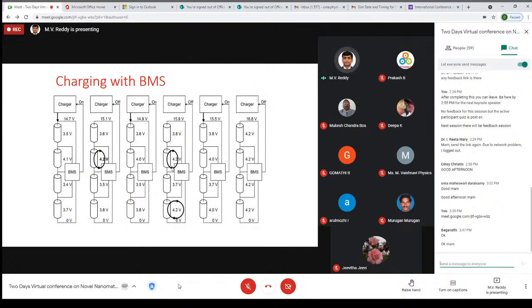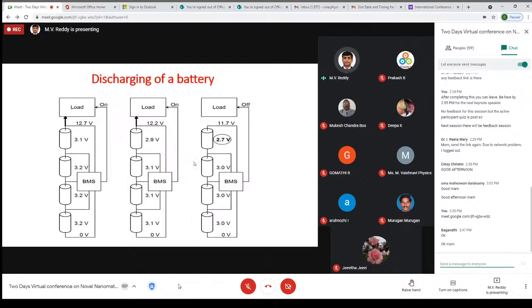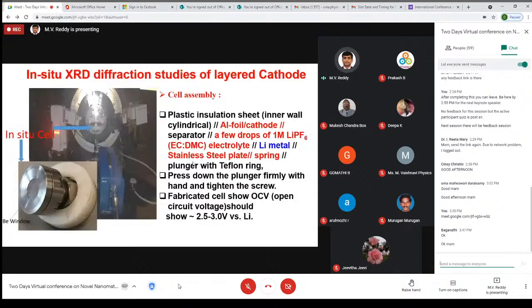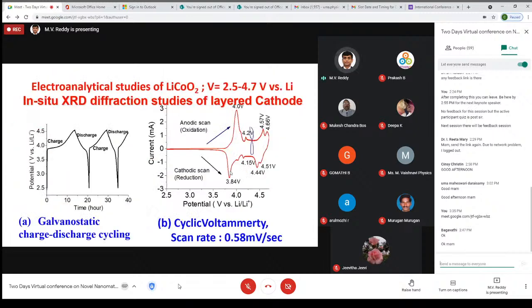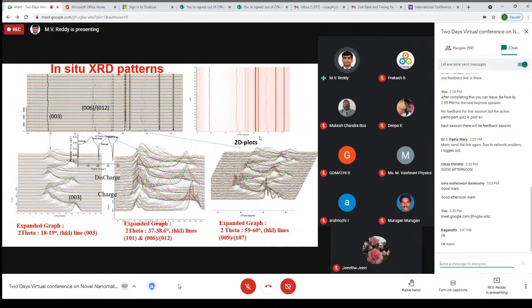If something is wrong with this BMS management, or during charge and discharge, or you have material issues, for example, people went to 4.6 volts instead of 4.2 or 4.3 volts. The reason is that we cannot remove the lithium too much; if we remove too much lithium, there is a huge volume variation, and sometimes oxygen is released with the electrolyte. Sometimes we can see bulging of the batteries, which clearly indicates some problem inside the battery. That's why, depending on materials, you also need to take the appropriate voltage into consideration.